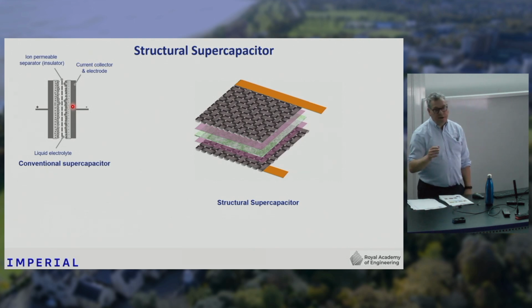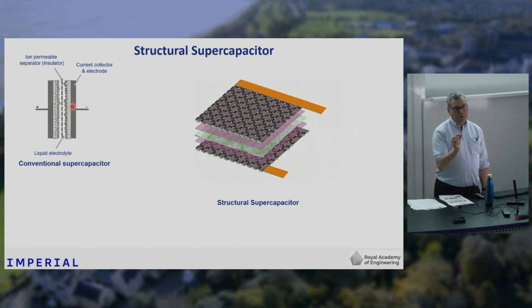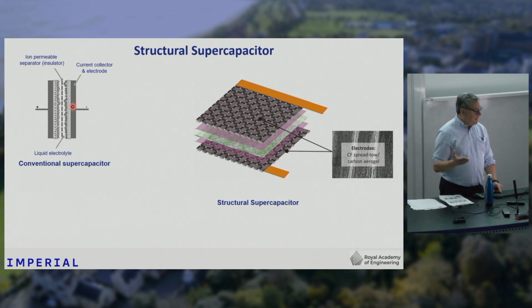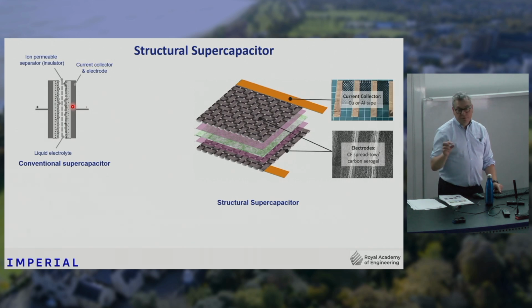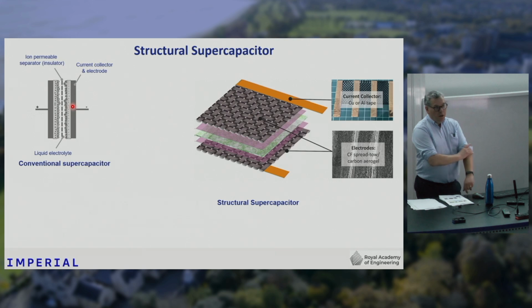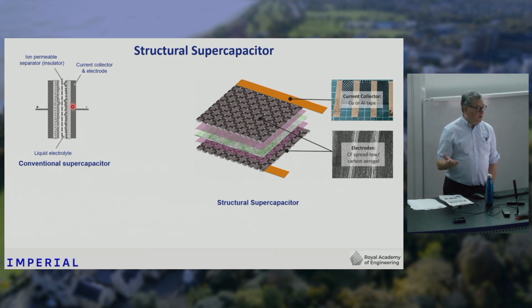Because you've got very high surface area and the charges are very close together, you get very high energy storage compared to a conventional electrostatic capacitor. So that's a conventional supercapacitor. What we've done is we've taken carbon fiber fabrics and recognized that carbon fibers don't have very much surface area, so we've done stuff to them to increase the surface area, and I'll talk a bit about that in a minute. We have current collectors, because although carbon is electrically conductive, it's not as good as something like copper or aluminium, so we have to put a current collector on there to help with that.